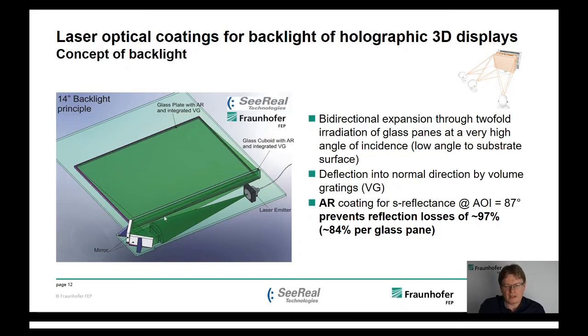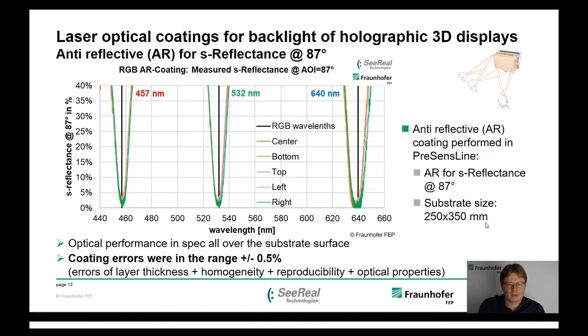Irradiation at this very high angle of incidence, 87 degrees, means 84% are reflected at each glass surface. And as there is 2 times this upscaling, 97% of the light is usually reflected. So what they need is an anti-reflective layer system for this light, to be precise, an anti-reflective layer system for the S reflectance at 87 degree angle of incidence. And we deposited this in our machine.